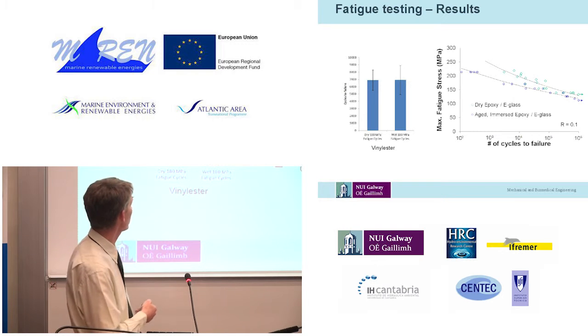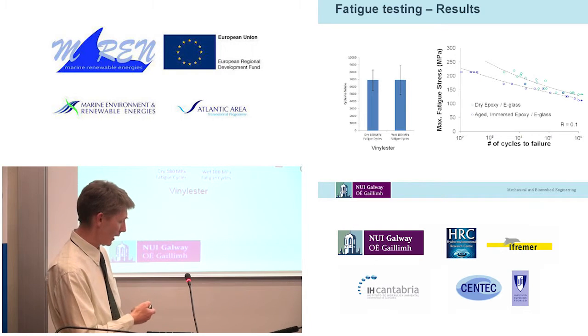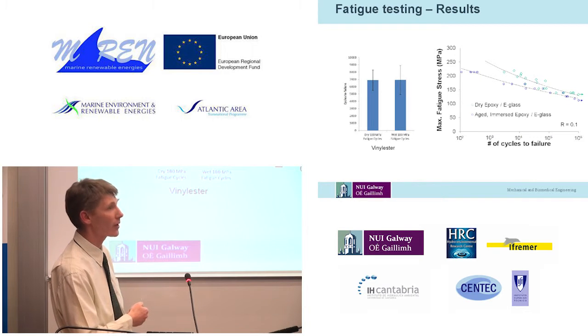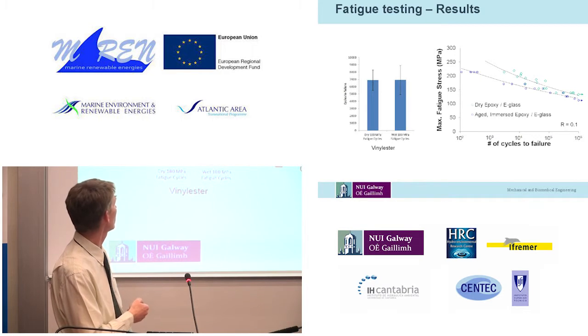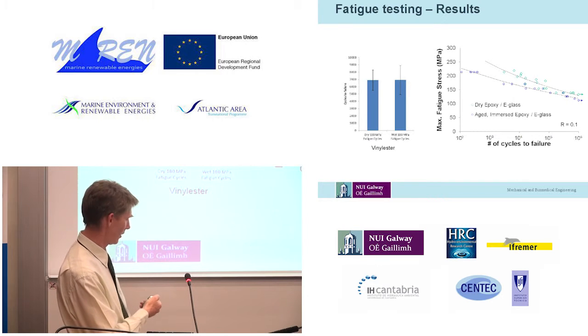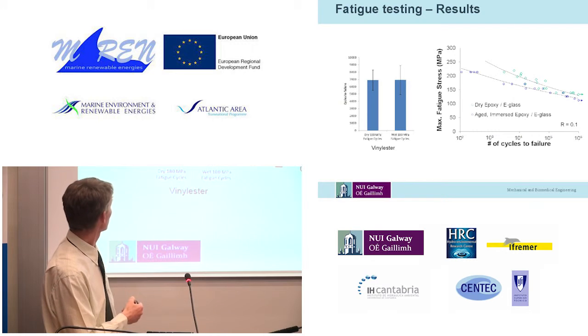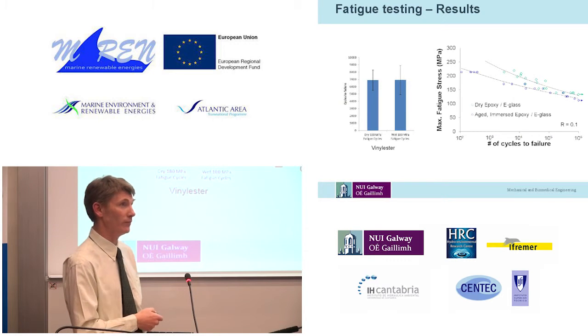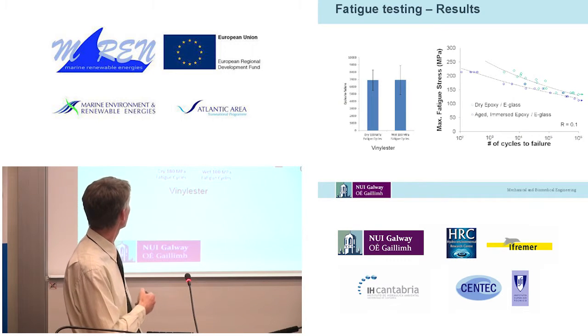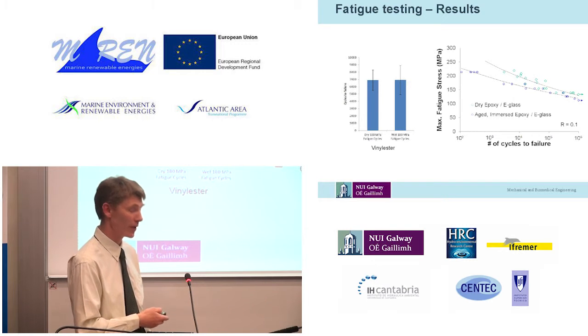Now, I've also done some tests on vinyl ester, not as many, but like I mentioned earlier, the water seems to have very little effect on vinyl ester, and in this case here at 180 MPa, I've found that there's almost no difference between a dry coupon and a saturated coupon.